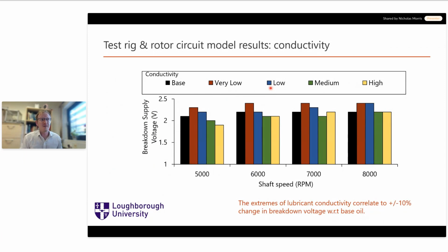And the way that these fluids have been formulated is that the additive pack is the thing that changes the conductivity. The base fluid stays the same throughout, and the viscosity characteristics are very similar throughout all of these, so that we can assume that the film thickness in the contact is very similar for all of these. So we conducted a similar breakdown voltage test to those that I showed on the previous slides. This is experimentally, and we can see that compared to the base oil, the low and very low conductivity additive packs correlate with a higher breakdown voltage, and then the medium and high conductivity additive packs correlate to a lower breakdown voltage than that of the base oil, if we take the base oil as a reference.